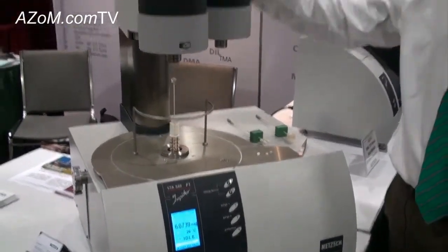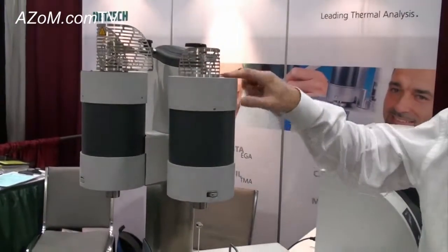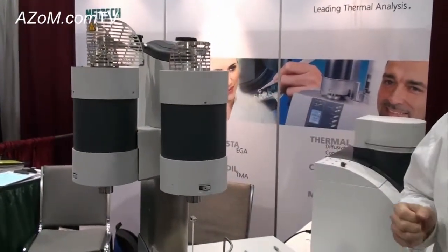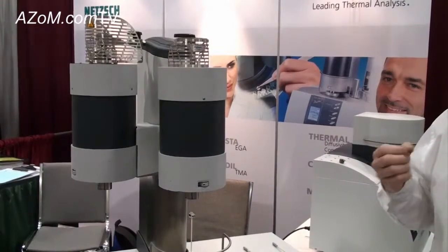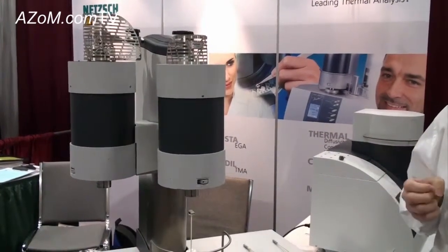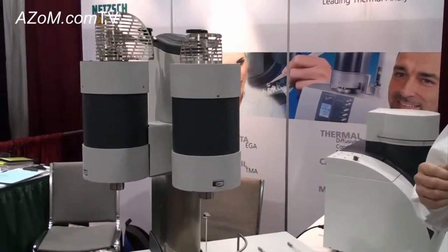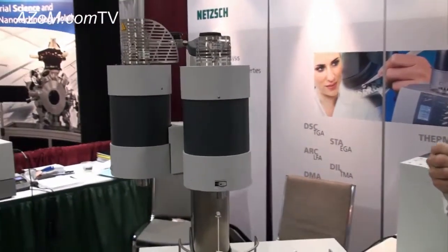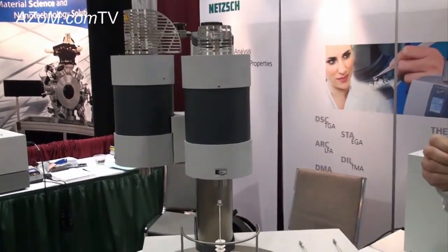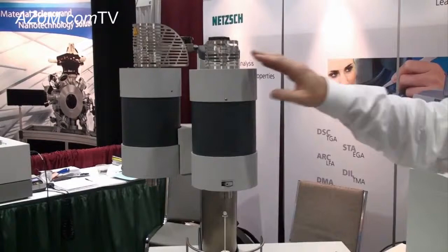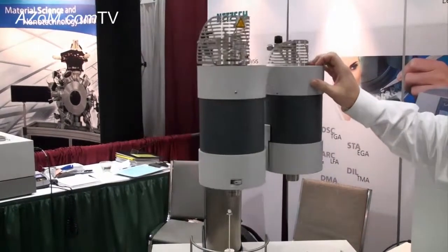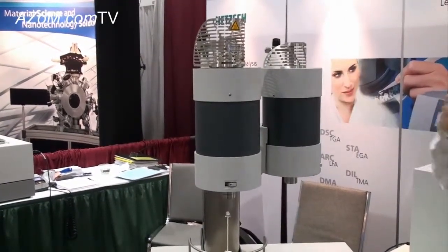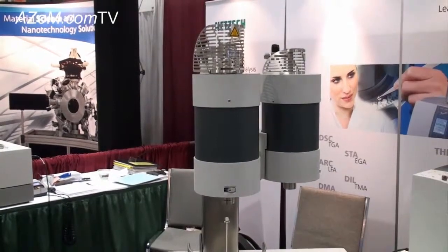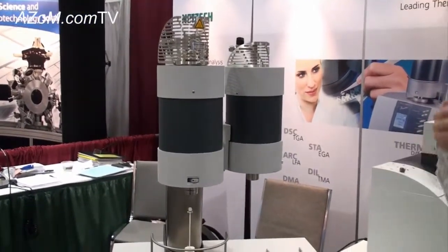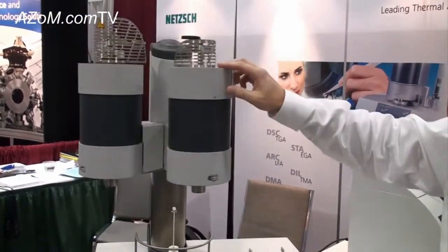We also have some special furnaces, such as this platinum furnace, for measurements of specific heat. So our instrument is very unique in that we can measure specific heat of a material with accuracy of plus or minus 3% up to 1400 degrees Celsius. And you can see we can have two furnaces mounted on an instrument. So we can extend either the temperature range or the application range by moving and selecting a particular furnace.